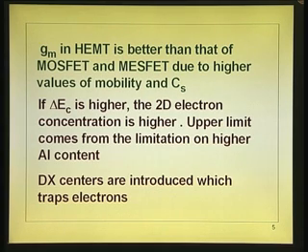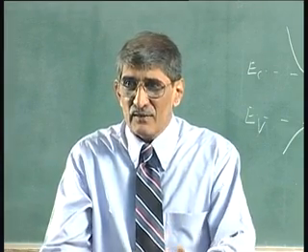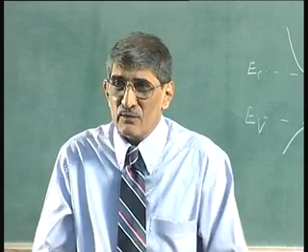We have taken the case where this x is about 0.4 or so, and delta EC is about 0.32 corresponding to that. Now, higher the delta EC, better ability to notch the electrons. You have got a well which is deeper, it will collect more electrons there.